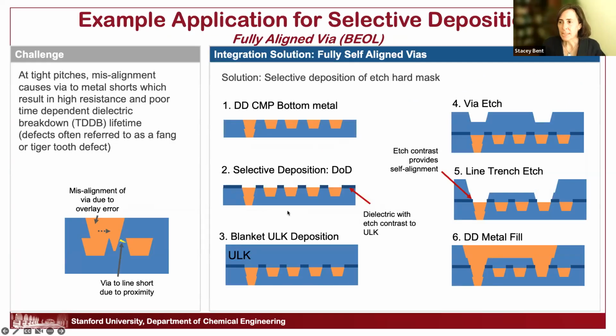I want to come back to this example of the edge placement error. And one of the approaches to solve that is to use these fully self-aligned via approaches. So this is for back end of line processing. And on the left here is that example that I mentioned before. If you have an overlay error due to misalignment, then you can have a line short, you can have other breakdown problems. So we want to try to avoid this overlay error.